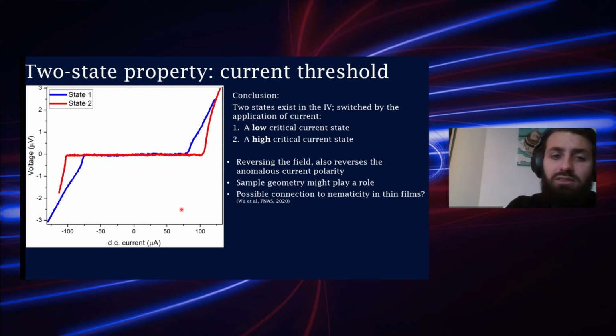Interestingly, when you reverse the magnetic field direction, the polarity having the anomalous hysteresis also reverses, so there seems to be some symmetry in the system. We found that this effect is normally revealed by applying an in-plane field along the ring, so we thought it has to do with the sample geometry. However, there are also different angles of fields where you see this behavior, and some angles that will never show it. So we're still trying to figure out why we see this, and at exactly what in-plane angles we find it.